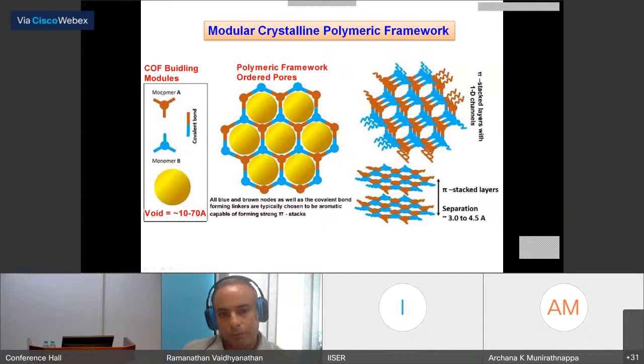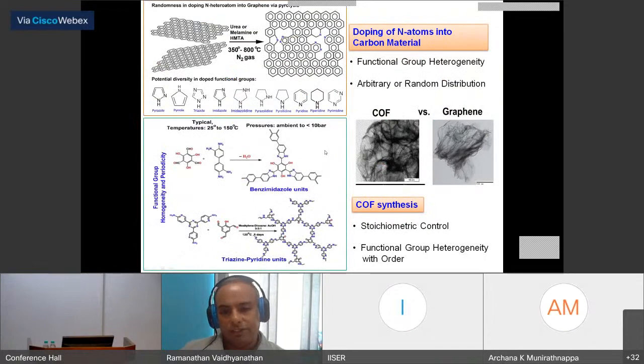And if you choose your monomers to be pi-stacking in nature, then you can get pi-stacking in the third dimension, giving rise to very ordered pores, which can be in the range of 10 to 70 angstroms, which are fantastic for many chemical manipulations. And another advantage that the covalent organic framework brings is this.